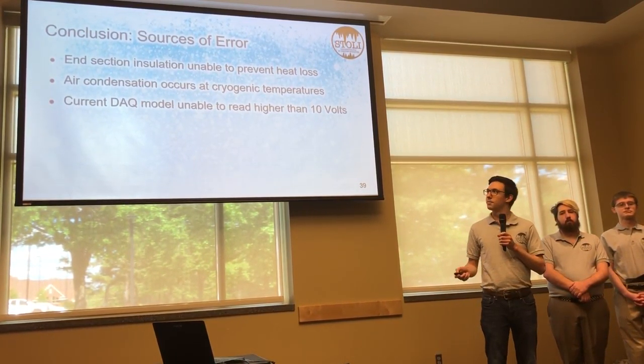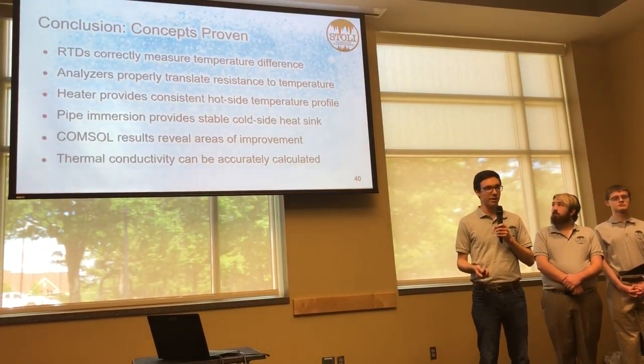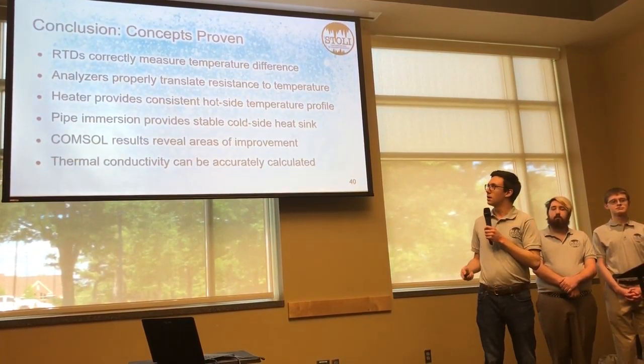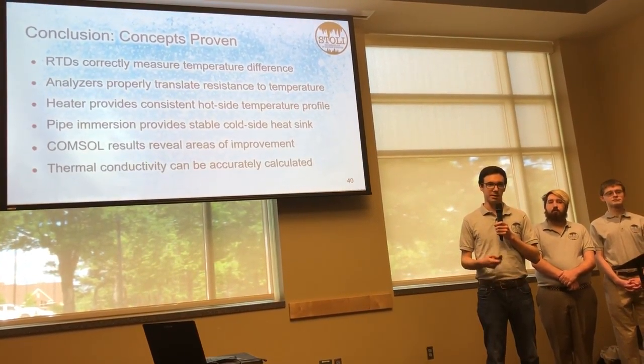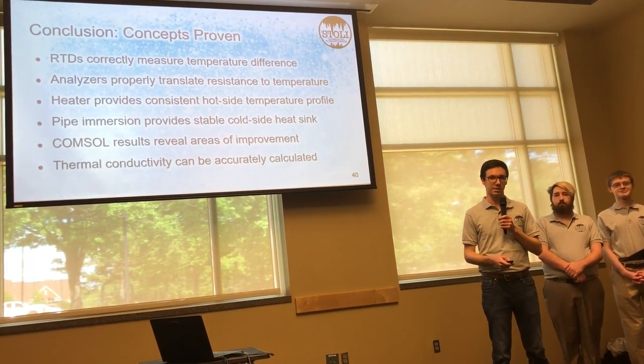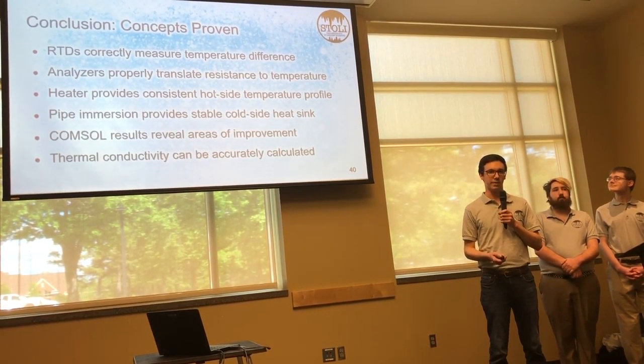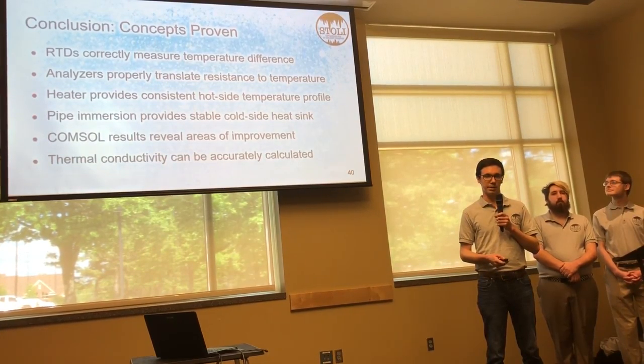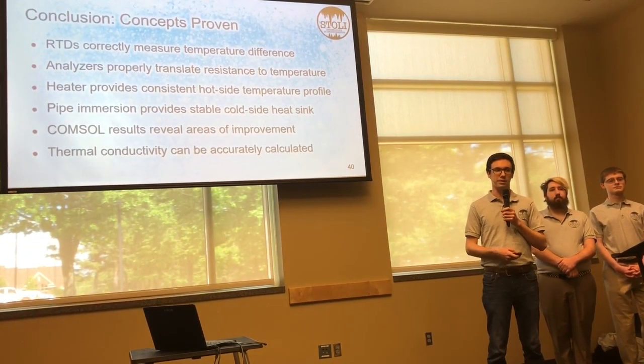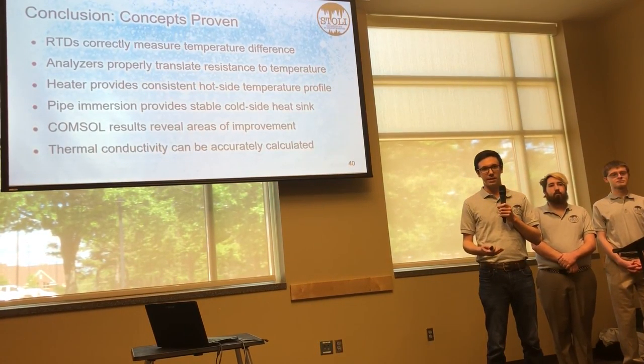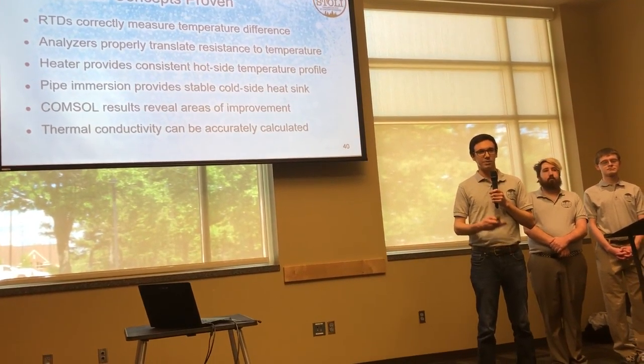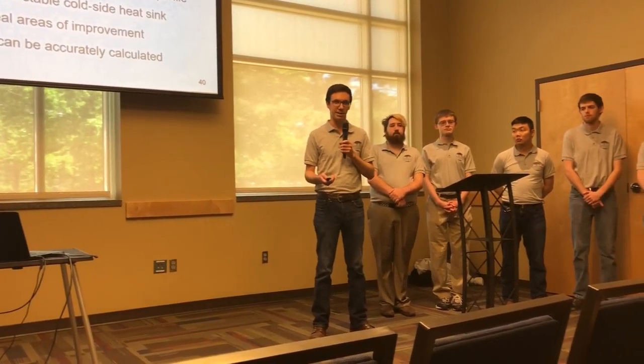Here are parts of our system validated as successful: our RTDs correctly measure temperature differences; our Excel and Python analyzers agree when converting resistance to temperature; our heater provides a consistent temperature profile along the test section; our pipe immersion technique provides a stable temperature bath; and our COMSOL results reveal where and how much we can improve. Our thermal conductivity calculation is accurate — it's just not accounting for axial heat loss, causing us to over-attribute heat to the radial section.